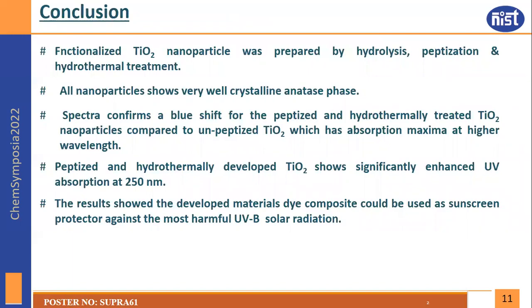So finally, in this work, we have presented the development of surface functionalized TiO2 by peptization and hydrothermal method. The hydrothermally developed particles show very good crystallinity compared to the peptized or unpeptized one. The spectral analysis confirms the formation of very small size nanoparticles on peptization and hydrothermal treatment. The peptized and hydrothermally developed TiO2 and its complexation with dye shows significantly enhanced absorption of UV radiation in the UVB region.